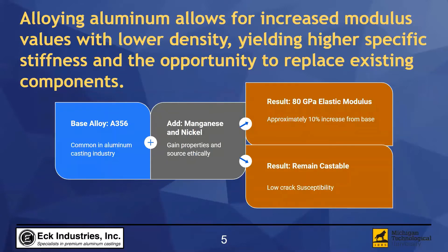With aluminum selected, the new alloy will use elements that are common in the aluminum casting industry. A356 is an inexpensive and well understood alloy, so the new design will add manganese and nickel in combination with A356, because these elements can increase the stiffness and be sourced ethically. The target modulus gain from the alloying is to be around 10%, moving from roughly 70 to 80 gigapascal. Finally, the alloy needs to be cast fairly easily without needing large-scale changes to a conventional casting process.